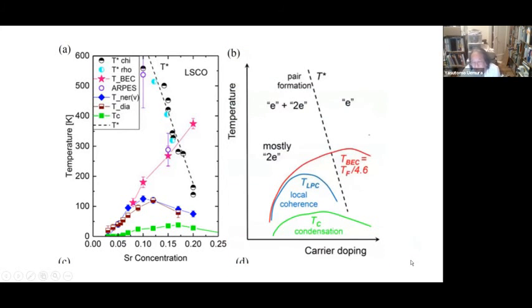And so phenomenologically, we can probably interpret this as showing that this Nernst effect is appearing when at least local phase coherence is achieved among preformed bosons. And that's why this is coming down close to this T star line. And the actual TC, as I always mention, is reduced by a factor of 4 or something on the underdoped side, and still reduced even in this optimally doped region.